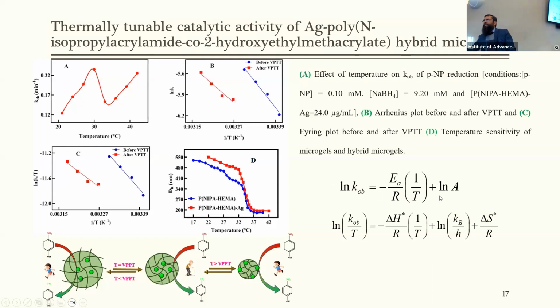We use the Arrhenius equation for the evaluation of activation energy and Arrhenius parameters. For this purpose, we plot the log of the rate constant as a function of 1 over T before the volume phase transition temperature and after the volume phase transition temperature, and the activation energy was evaluated from the slope, while the pre-exponential factor A was evaluated from the intercept of the Arrhenius plot.